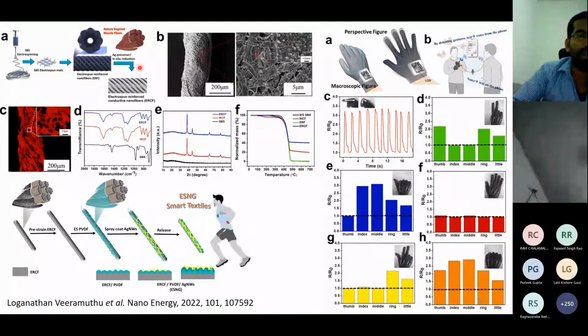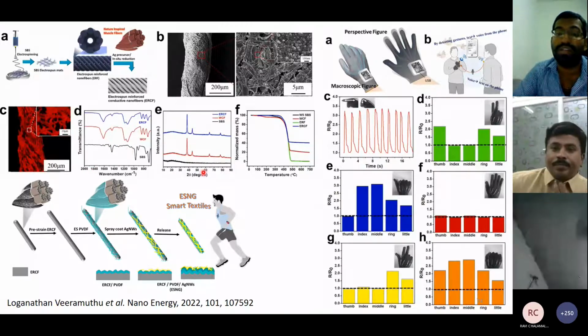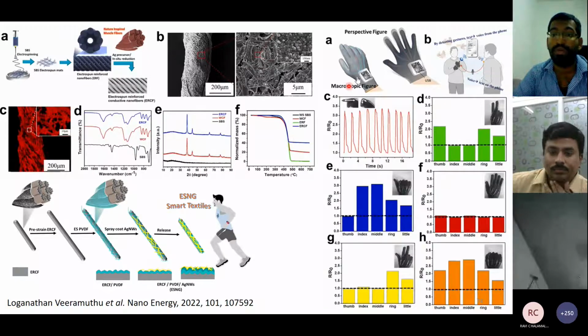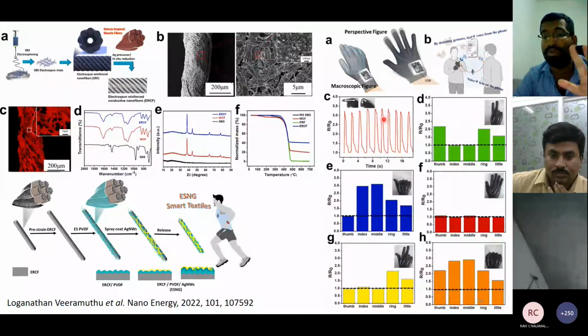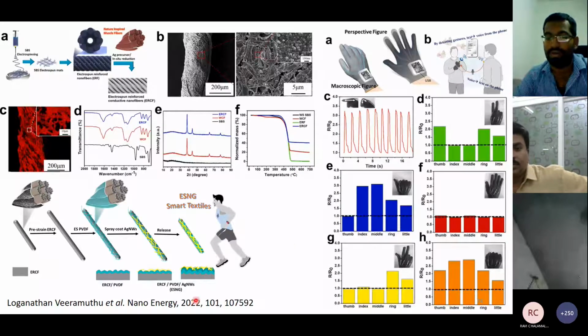And here, how we prepare this kind of structure is given. We use electrospinning, and then we are able to form electrospun reinforced nanofibers, and then we use some silver nanoparticles. Here you can see how the nanofibers look. It's a microstructure, and the nanoparticles are visible here within 100 nanometers maximum, so the average is around 60 to 70 nanometers. Then we confirm the presence using EDX, and we studied the functionality, crystallinity patterns, and thermal stability. And then we use them on wearable gloves like this. If we make some motions using this kind of resistive structure, we are able to monitor them, and for someone making sign language, we can easily understand what they are saying. So with these kinds of things we are able to do this.